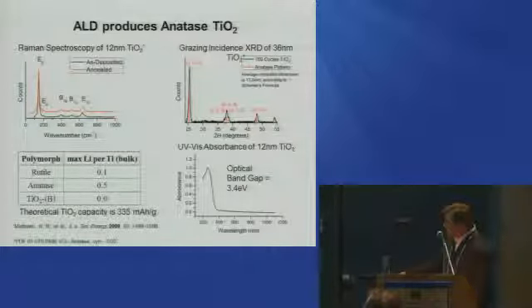And if you predict, based on the number of sites, you would predict that roughly you could lithiate TiO2B to about 335 milliamp hours per gram. Multiply that by 3.6, and that's coulombs per gram. Whereas the other materials have been shown to not lithiate as much.